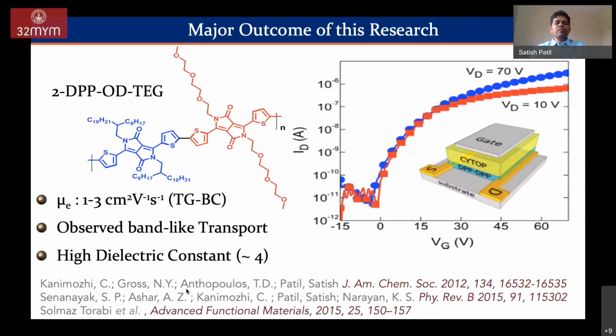So the major outcome of this research project is that we indeed found very high electron mobility in a field effect transistor geometry. The electron mobilities were 1 to 3. We observed band-like transport, which is a very unique phenomenon in a pi-conjugated system, very rarely observed so far in the literature. And this polymer has polar side chains. It has a very high dielectric constant. So we could achieve a very unique class of property in a pi-conjugated polymer rationally designed in our lab.